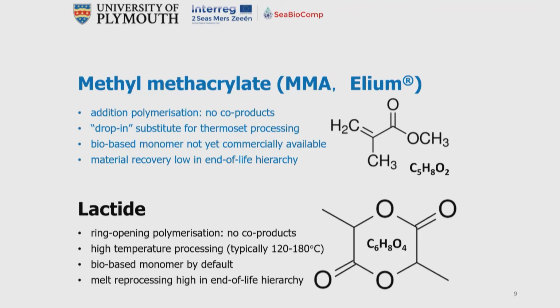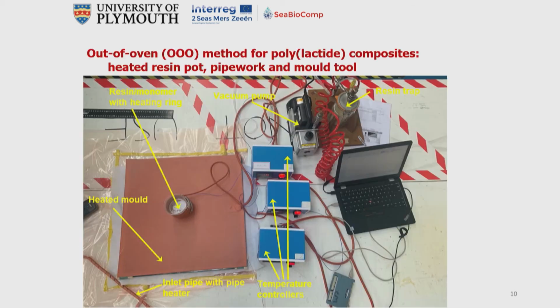The lactide is a ring opening polymerization, so again, there are no co-products to deal with. But it's a high temperature process, typically 120 to 180 degrees centigrade, because it comes as a solid powder. It's a bio-based monomer by default, and melt reprocessing is high in the end-of-life hierarchy. So we're beginning to see that even with our limited set of potential monomers, there are constraints, and there isn't a perfect material. We did this at relatively small scale.